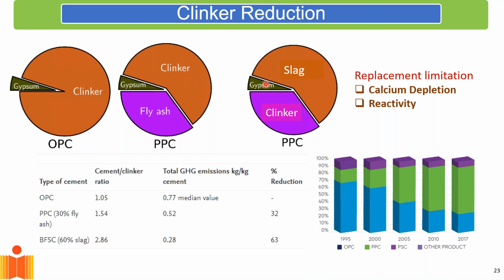Now, I can decrease my clinker factor even more if I go to PSC, the slag cements. Here, the story completely reverses, where I can go up to 70% of slag and only 30% of clinker. So now the story is completely reversed. Here I'm talking about a very low clinker factor cement, so it will definitely have a net positive impact on my total carbon contribution coming from the cement.